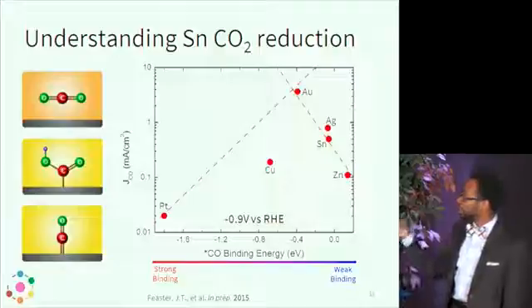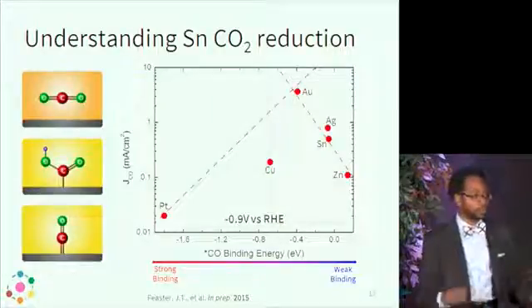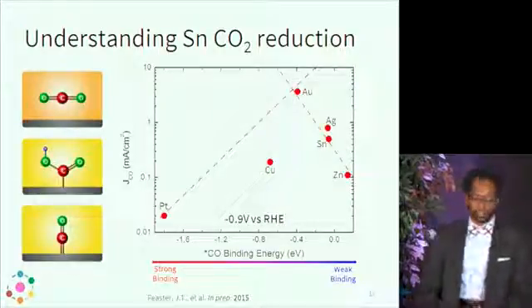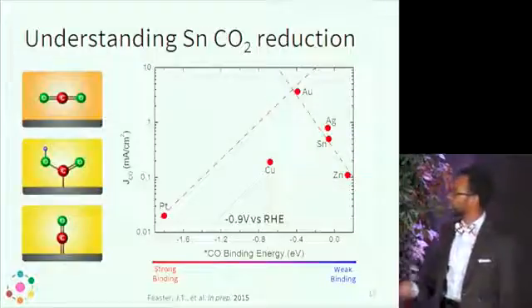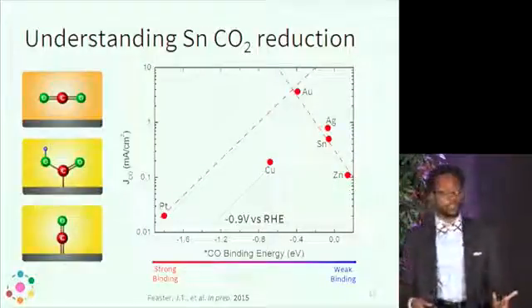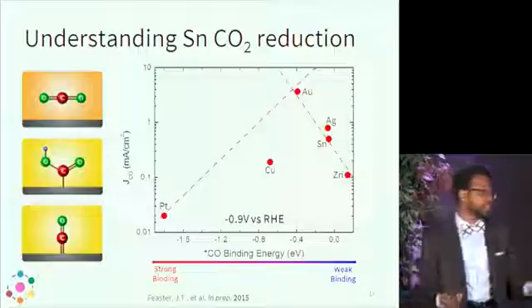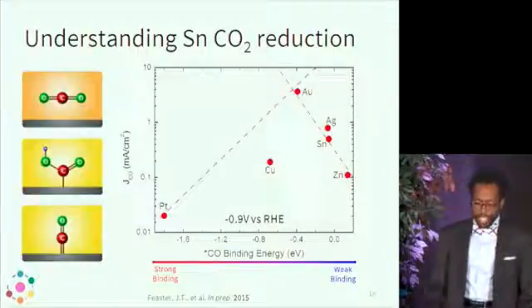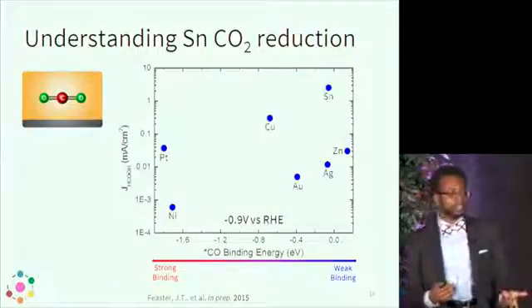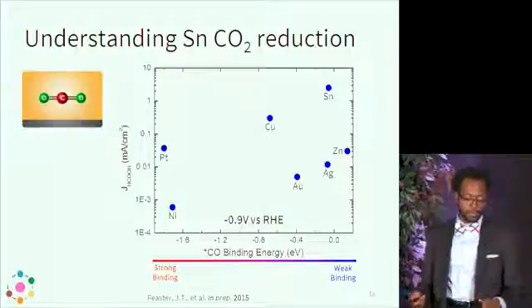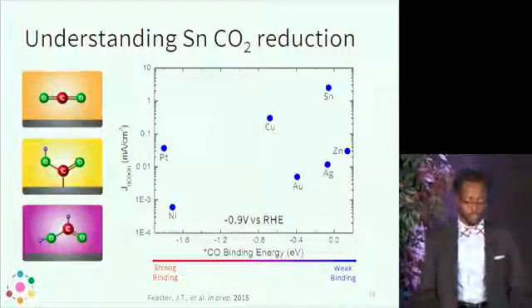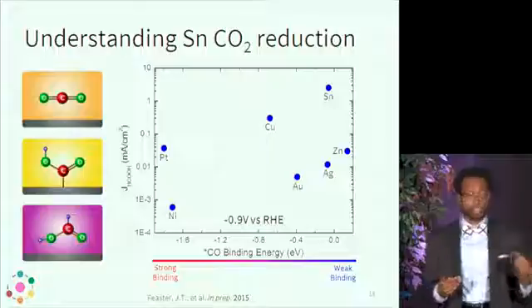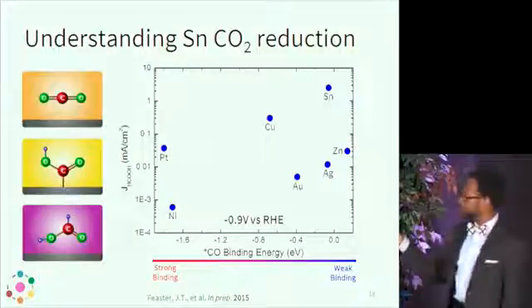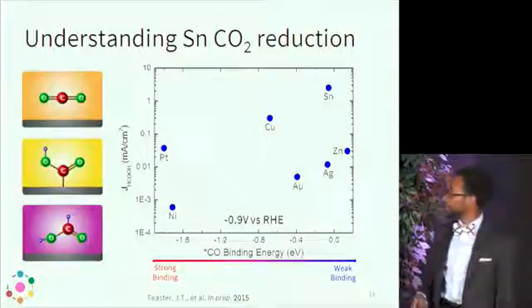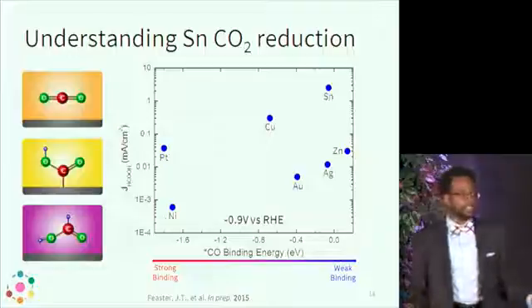And so as you can see here, tin seems to fit very well within this framework for carbon monoxide production, where it's on the weak binding side, and the production rate that we're actually being able to observe matches very well with what we would expect theoretically. However, when we do the same calculation, looking at the same type of intermediate here, the carboxylic acid intermediate, but looking at formic acid production, as you can see at the very bottom left of the plot, the trend completely disappears.